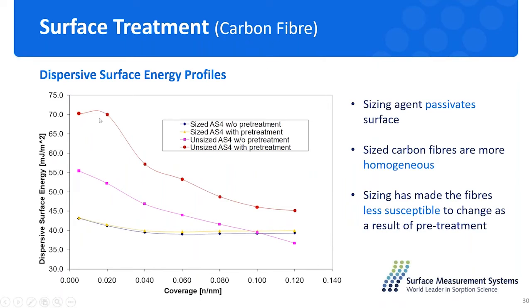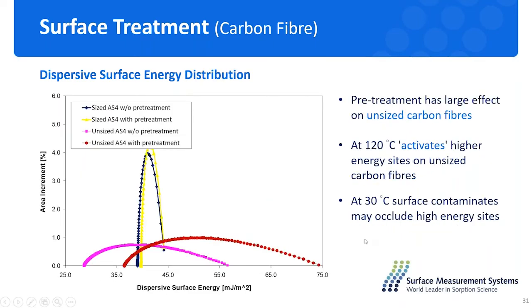So here we find that the red line and the pink line for the unsized carbon fiber have a large variation between the high energy site and the low energy site, changing dramatically as a function of the surface coverage. And after sizing, the surface of this carbon fiber is passivated, and the sample also becomes more homogeneous, not changing a lot with the surface coverage. And it is more illustrative in this distribution that the temperature has more effect on the unsized carbon fiber, with higher energy for the 120-degree treatment compared to the 30-degree treatment, which is probably due to the removal of contaminants on the surface or also opening up, activating the energy sites.